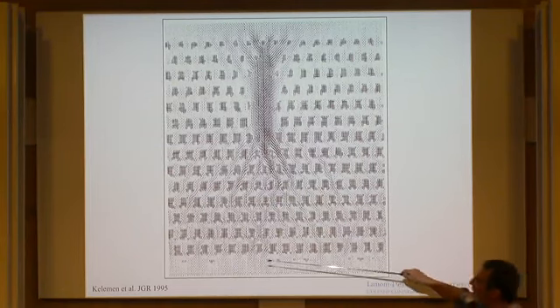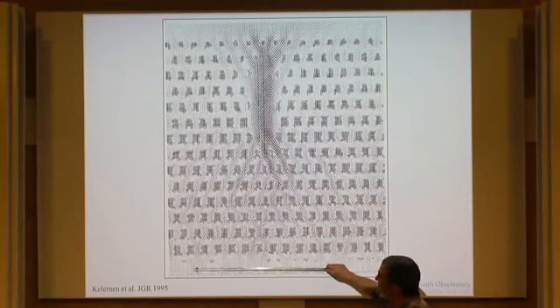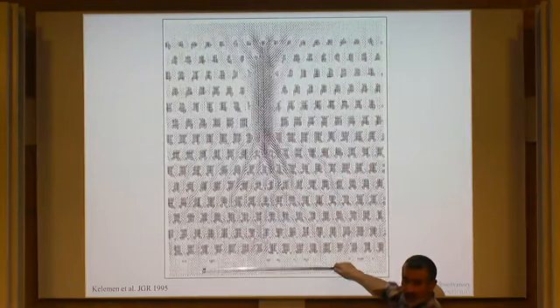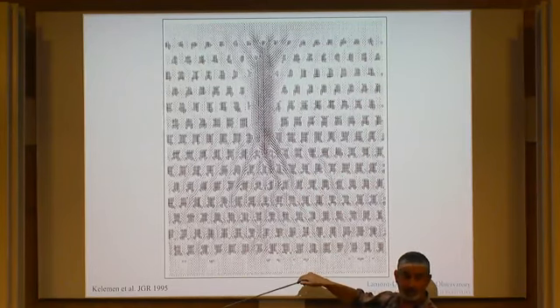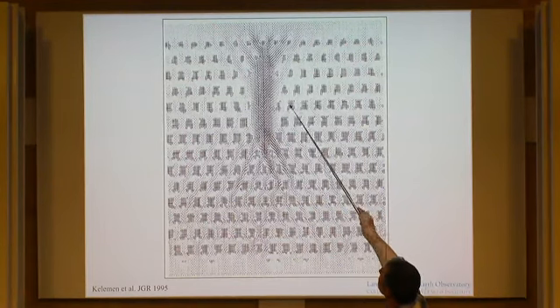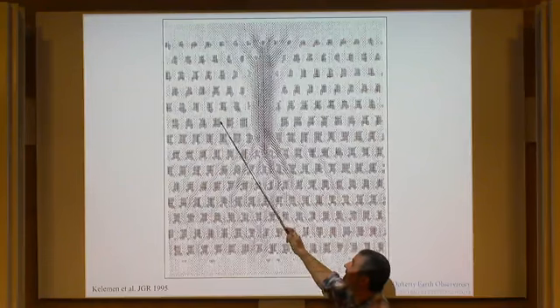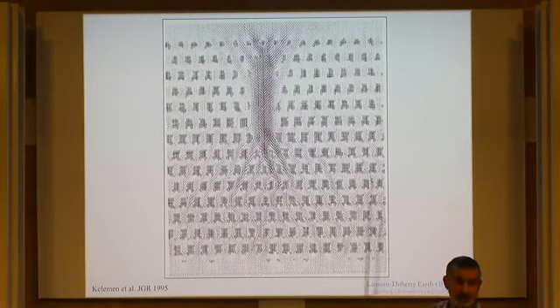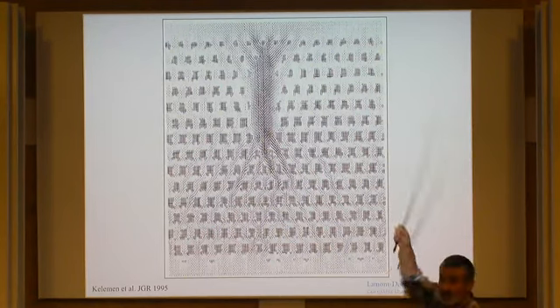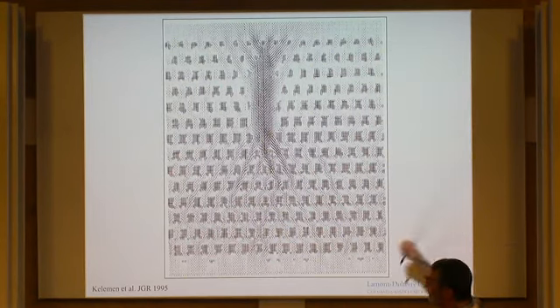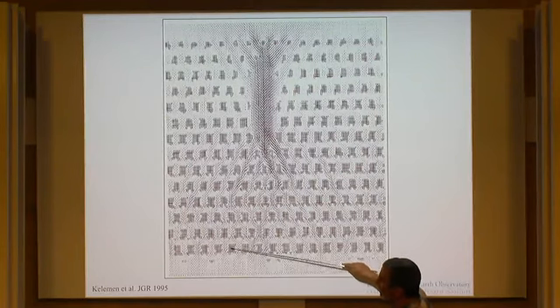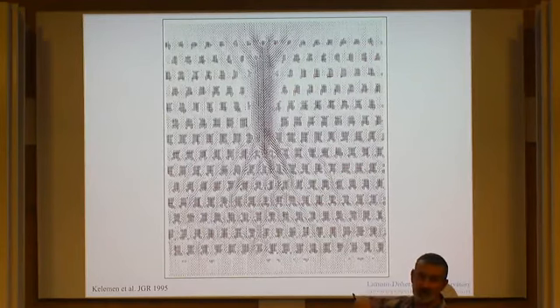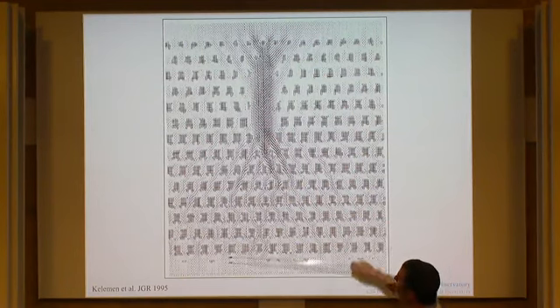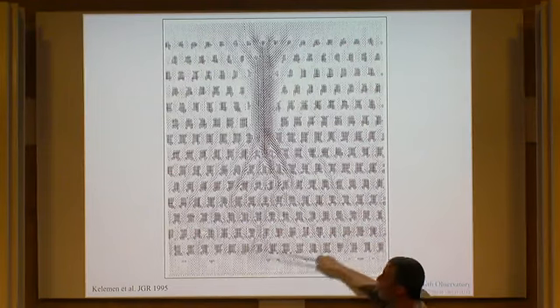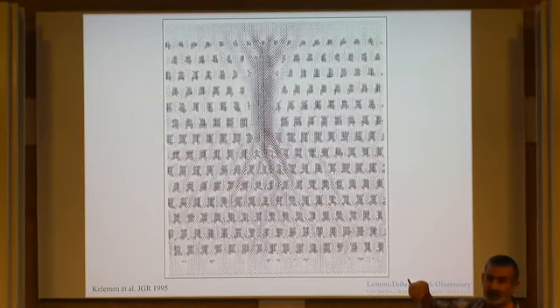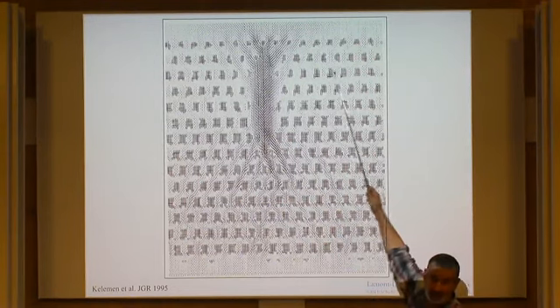And we had a fluid that was represented by elastic little billiard balls, and you could imagine that the billiard balls coming in the bottom of this box are blue. And then we had solid particles that you can imagine were red, that are just sitting there in the way. Okay, you've got these elastic billiard balls bouncing their way down through a pressure gradient. And there's some probability that when a blue ball hits a red square, it'll detach a red fluid particle. And we have a solubility gradient, so the probability of detaching a red fluid particle depends on the concentration of red fluid particles. And it goes up as you go up through the box.